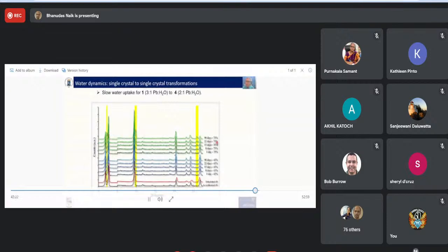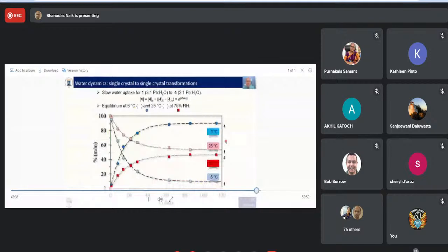And then, even after 90 days at 75% humidity, and this is at room temperature, you can see that you haven't formed fully 4 yet. So it's a really slow process going to form. And he actually studied the kinetics of this.